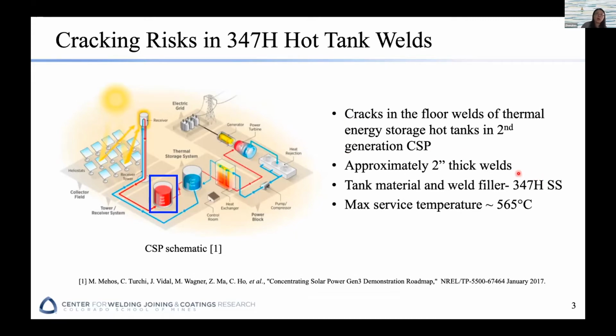Our industrial collaborator informed us that there are cracks observed in the floor welds of those thermal storage hot tanks in the 2nd generation CSP system. And the filler material that they were using is 347H as well. The maximum service temperature is 565 degrees Celsius, and the thickness is about 2 inch.